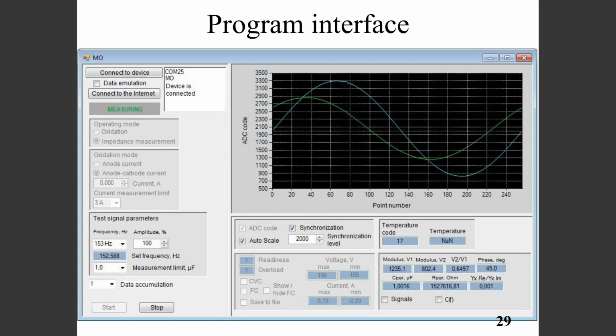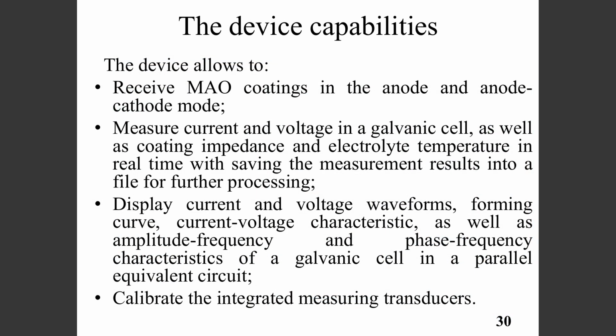In this figure, several functional areas can be distinguished: connection area, area for setting operating modes, oxidation and impedance measurement, graphic display area of signals, area for controlling the graphic display of signals, area of oxidation parameters, impedance measurement parameters area, and electrolyte temperature display area. The device allows one to receive microarc oxidation coatings in the anode and anode-cathode mode, measure current and voltage in a galvanic cell, as well as coating impedance and electrolyte temperature in real time, with saving the measurement results into a file for external processing. It displays current and voltage waveforms, the forming curve, current-voltage characteristics, as well as amplitude-frequency and phase-frequency characteristics of a galvanic cell in the parallel equivalent circuit, and calibrates the integrated measuring transducers.